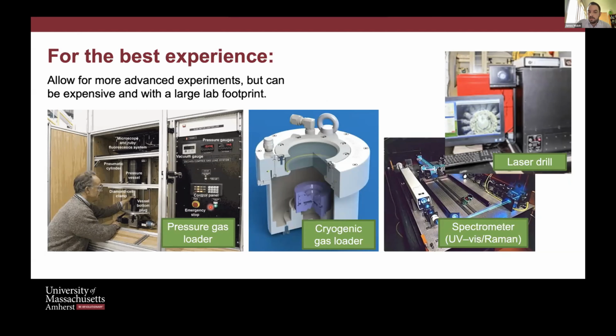To get those gases into the cell, you have to use some tricks, and that's either by loading it with high pressure. So you put the whole cell into a chamber and you put so much pressure that it condenses that gas. And then when you get enough of it that it flows into the gasket, you can then close it with some remote operation. You pinch the diamonds and you trap that gas at some pressure, and then you recycle the gas. That works really well. It's an expensive and very large instrument.